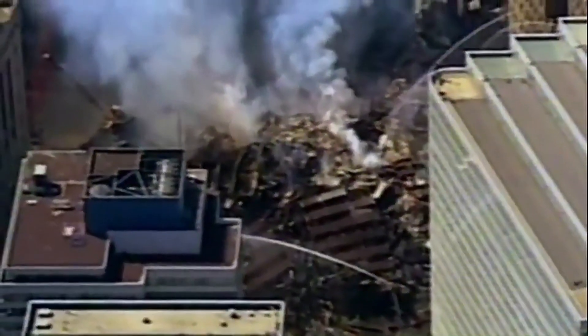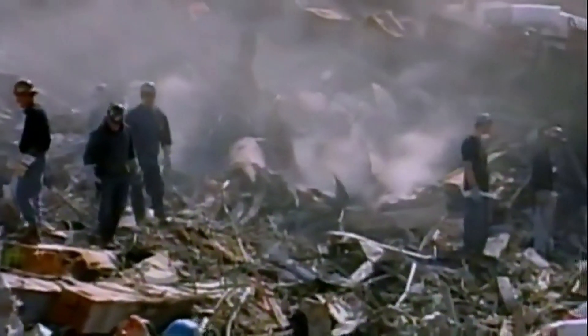Professor Sisson says it didn't melt — it eroded. The cause was the very hot fires in the debris after 9/11 that cooked the steel over weeks. The sulfur came from masses of gypsum wallboard that was pulverized and burnt in the fires. I don't find it very mysterious at all that if you have steel in a high-temperature atmosphere rich in oxygen and sulfur, this would be the kind of result you would expect.